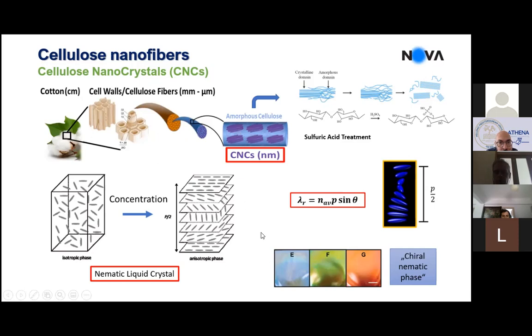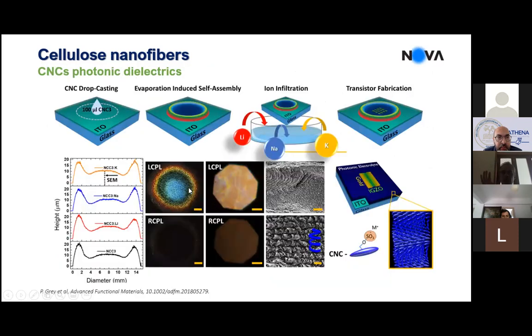So you can make membranes that are green, red, blue, that have these characteristics under circular polarized light, because the self-assembly makes a kind of rotation, and this is very good as a filter for circular polarized light. This is a left-handed rotation, and these structures reflect left circular polarized light. So if you have a filter for left CPL, you see colors, and if you have a filter for right CPL, you don't see color, because the right CPL light will pass through the structure.